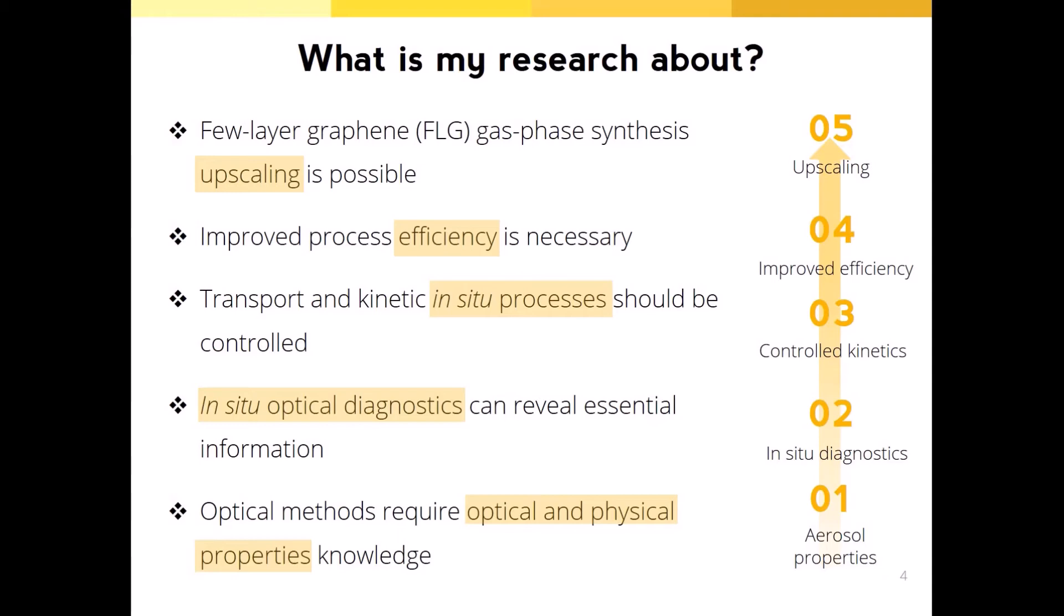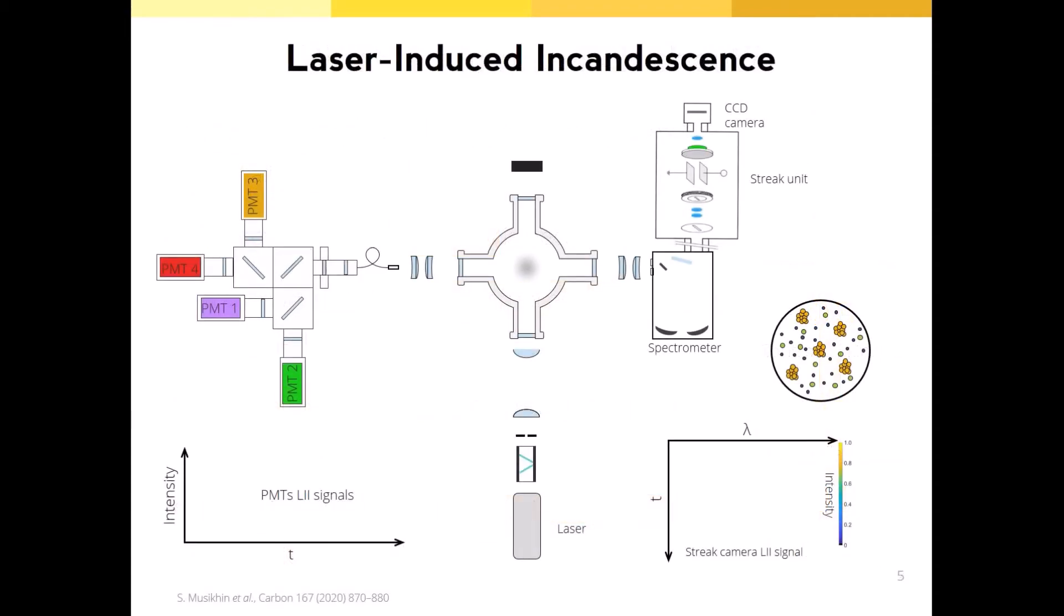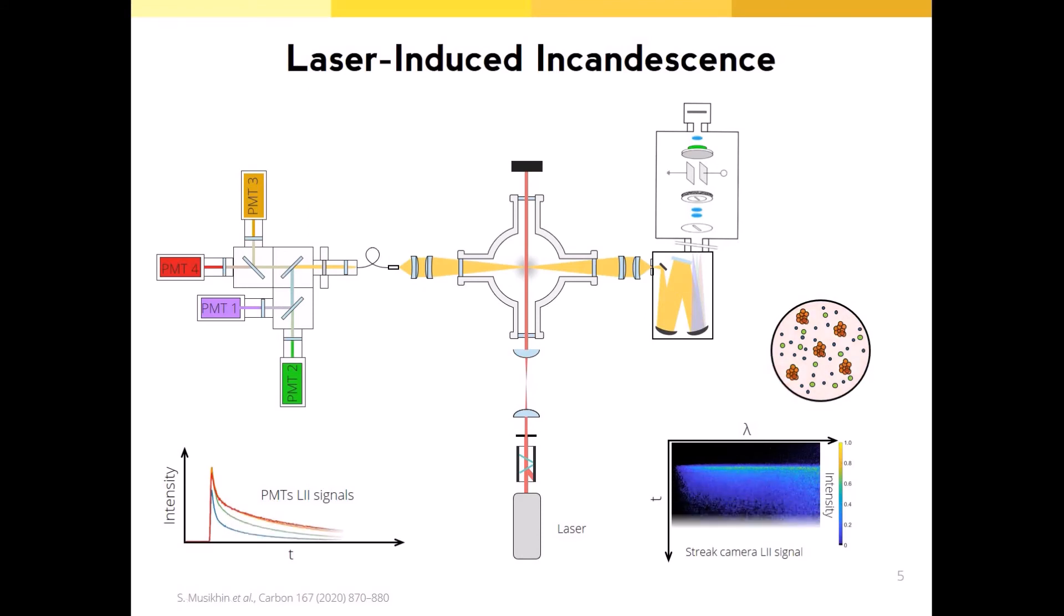There are a few laser-optical diagnostics we are planning to deploy, and the first one is laser-induced incandescence. The idea behind laser-induced incandescence is the following: this is a reactor with graphene aerosol produced inside. The nanoparticles in a probe volume are heated by the laser pulse to temperatures high enough so they can emit detectable thermal radiation incandescence.